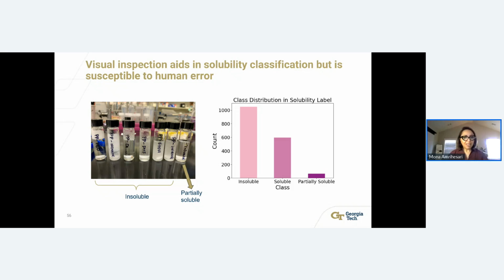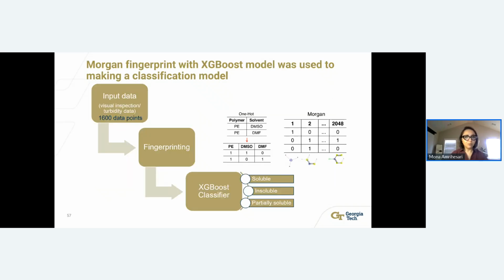What we validated is that we had the same data from the visual inspection as we had from the Crystal 16, using almost the same polymer and solvent solutions. We tried to match it up, with the same number of data points and the same machine learning and fingerprinting methods, and classified them as soluble, insoluble, and partially soluble, even for the Crystal 16 data. So we classified those based on the cutoffs that I introduced.